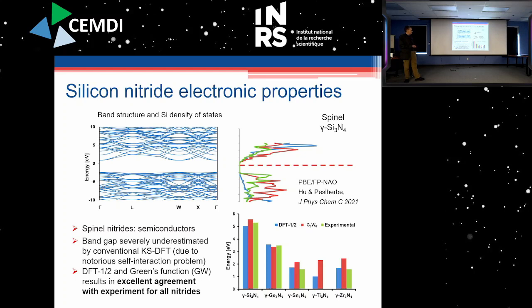And we can fix this by using more elaborate methods here. And it turns out that when we take into account this more elaborate treatment of the electronic structure, we end up with band gaps that are in excellent to very good agreement with known experimental data. All right. So all that to show that we know how to handle the situation for these materials and reproduce experimental observables with some confidence, right? Which again brings a level of confidence into our own calculations and predictions.